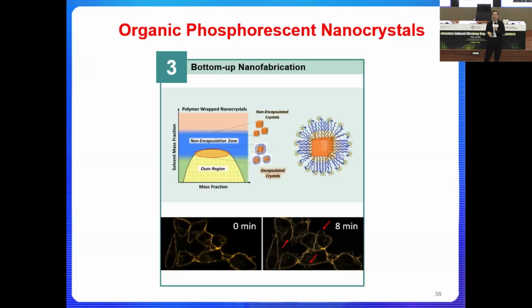All right, so we went back to the phase diagram, and I understand nowadays phase diagram is no longer popular among the younger generation, but it's so important scientifically that it will allow us to find the optimized condition to make nanoparticles, and more importantly, nanoparticles that are crystals. For any organic molecule that is to be wrapped with block copolymer to form the core-shell or micelle structure, we can actually refer to this phase diagram. What we care a lot about is this zone, where the right solvent and solute combination will allow the block copolymer to form nanoparticles that will wrap the organic molecules at the center.